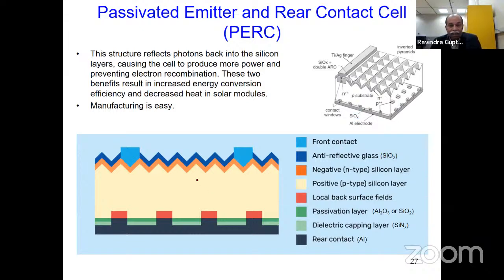Okay, so this is the cell design. You can see here, this is the front contact made of silver, and nowadays we are using Ti also. This is the anti-reflecting layer, SiO2. This is the quartz glass. This is the inverted pyramid style. Then we have the negative N-type material, very, very thin. Then we have the P-type silicon layer here. These are crystalline material. And then we have the local back surface field. And then we have a passivation layer, which is made of alumina or SiO2. Then we have the dielectric capping layer, silicon nitride. Then the back contact made of aluminum.